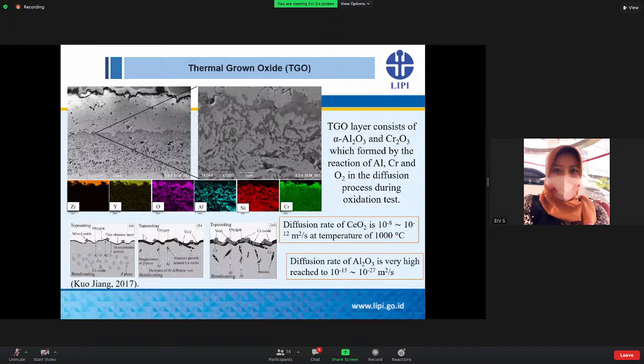The mechanism of the TGO formation could be explained by the work already published by Kuo Jiang in 2017. So this is simply a description of this mechanism. At the beginning, there is precipitation of a layer. And we have known that the diffusion rate of the aluminum is higher than the cerium dioxide. So the thin alumina will be formed continuously, as you can see in the top layer here, as in some parts of the outermost alumina scales.